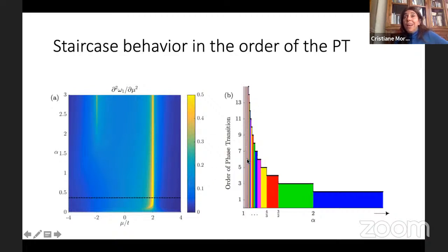Actually, we could show analytically that the order of the phase transition here in this regime between alpha equal 1 and 2 is increasing as a devil's staircase. So it is second order for alpha larger than 2, but between alpha equal 3/2 and 2 over 1, it's third order. Between alpha 4/3 and 3/2, it's fourth order. Between 5/4 and 4/3 is fifth order. And it goes to infinite order as you reach 1. So it's a very anomalous behavior.